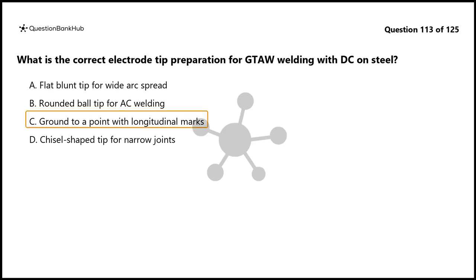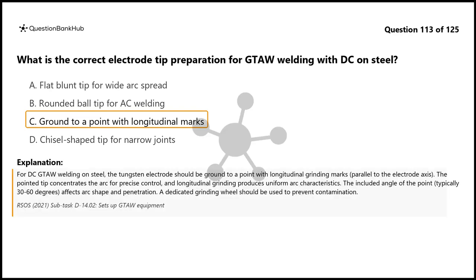The correct answer is C. Ground to a point with longitudinal marks. For DC GTAW welding on steel, the tungsten electrode should be ground to a point with longitudinal grinding marks, parallel to the electrode axis. The pointed tip concentrates the arc for precise control, and longitudinal grinding produces uniform arc characteristics.